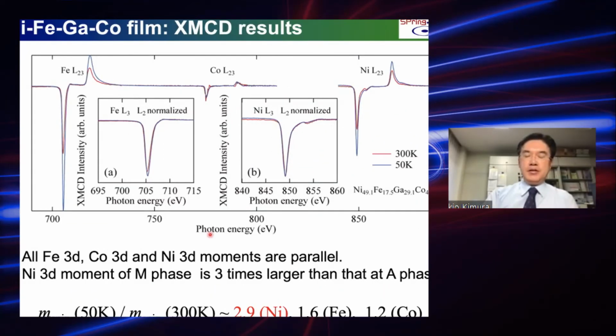So here's the result of the X-ray magnetic circular dichroism experiment in order to get the element-specific magnetic moment. You can just tune the photon energy to get the magnetic moment on the specific element. For example, at the iron 3D edge, you see the negative peak here and the positive peak here. And for cobalt and nickel sites, you also see similar behavior, but with a different amplitude of dichroism. So we know from this result, with the same sign of the dichroism, that the iron 3D, cobalt 3D and nickel 3D moments are aligned parallel.